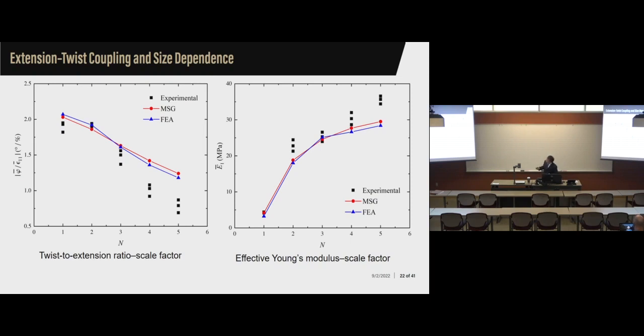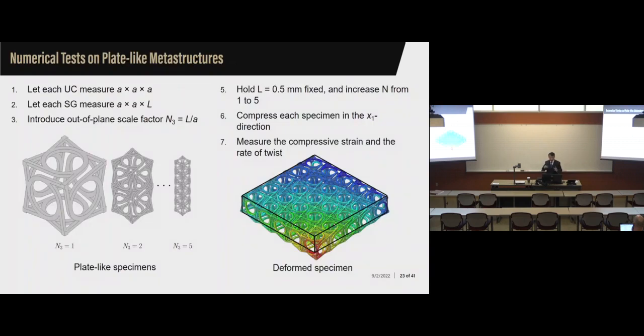And this is the results. In that paper, they did the experiments, and also the FEA results are from their paper. And the MSG results is here. We have a pretty good agreement with the FEA results done in that Science paper, and to try to examine the size effect with respect to the scale factor. That's for the beam level, which means the unit cell will be repeating along one of the directions. And if you have a plate, which is the unit cell repeating along two of the dimensions, you will also have this twist and bending and extension and twist behavior.